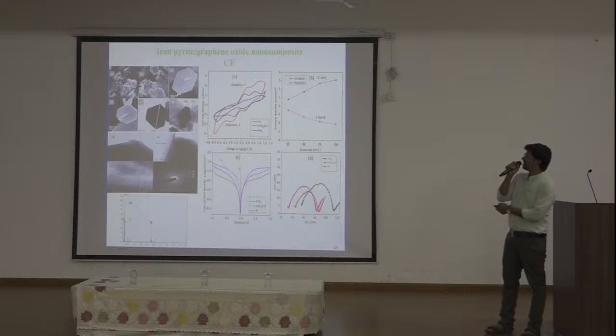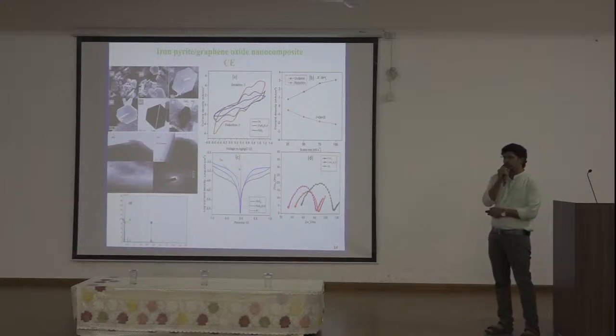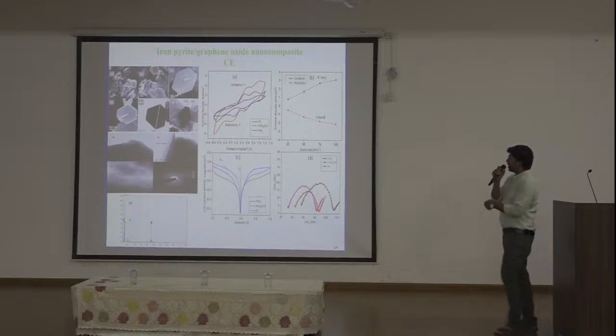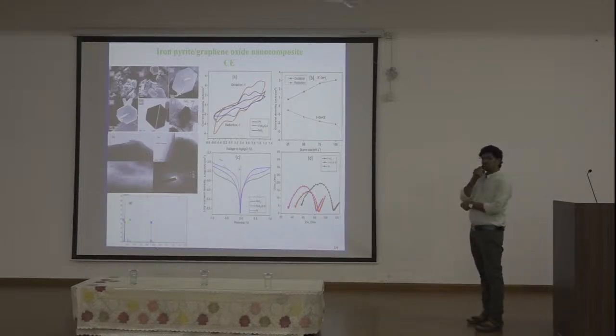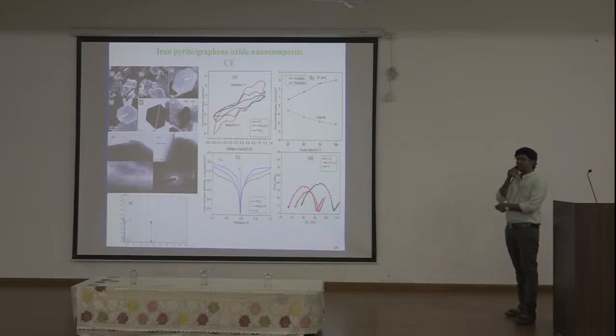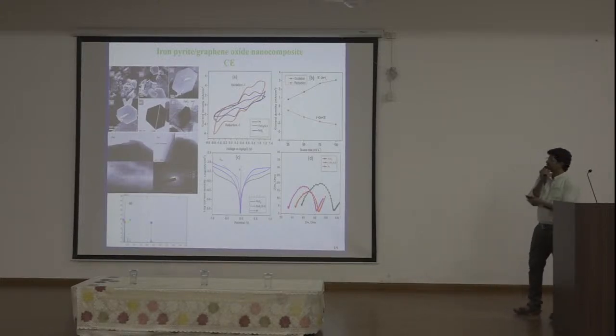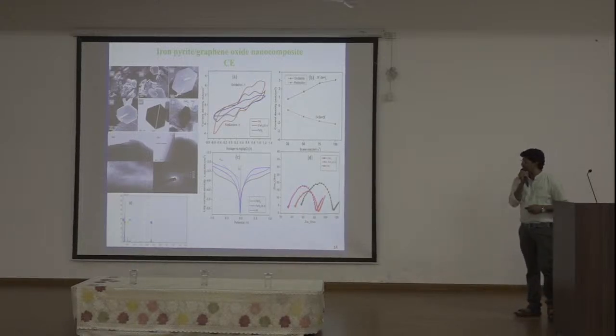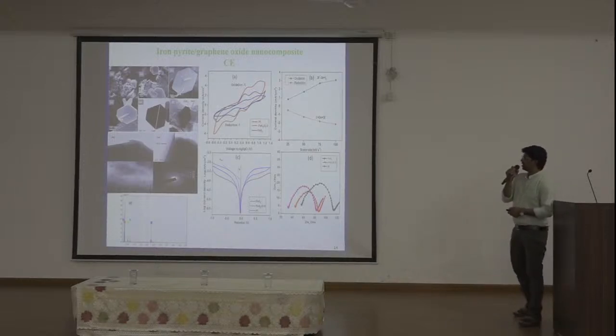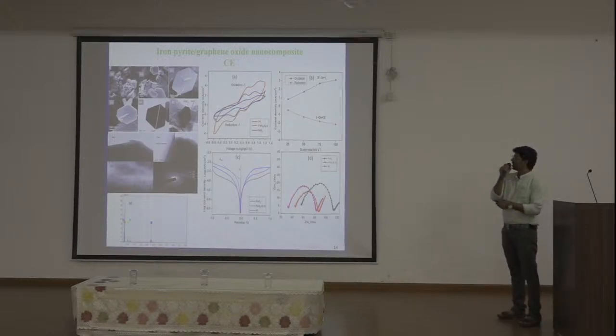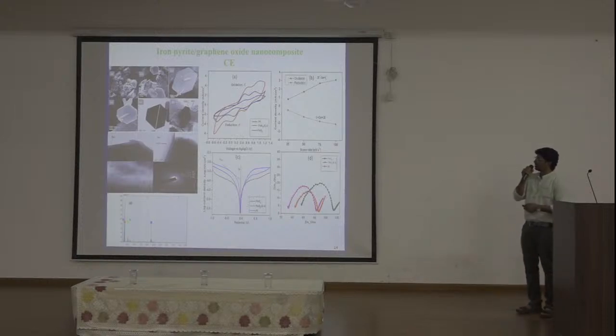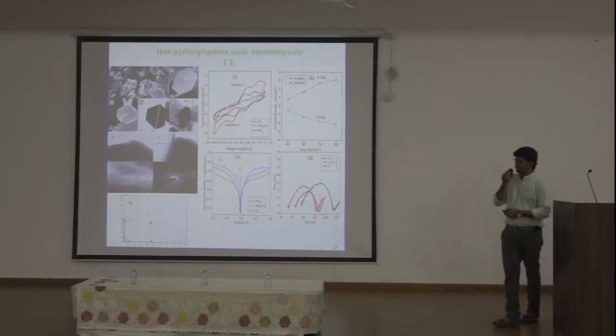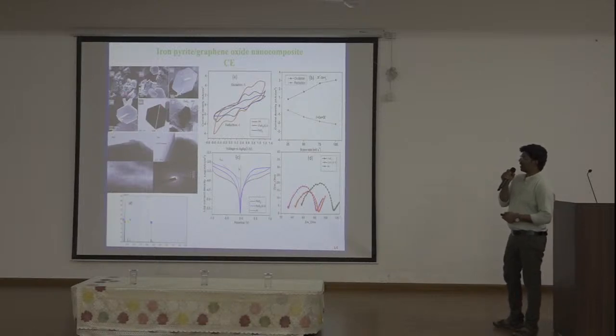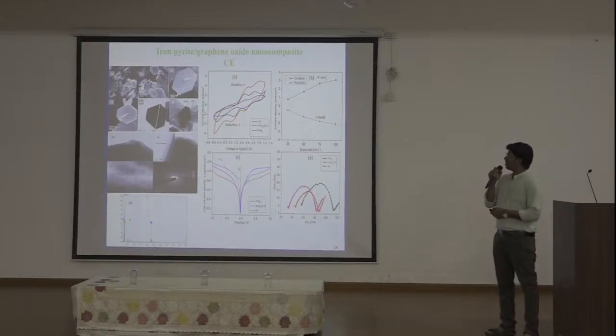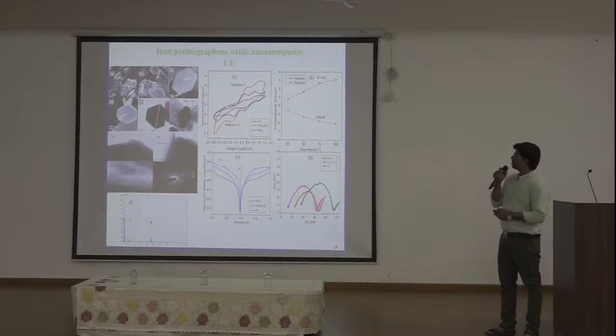Initially we tried iron pyrite and RGO composite. Second, we also tried the transition metal, especially the pyrite material, and its behavior as a counter electrode, checked in the graphene oxide composition. In this, I didn't show the basic characterization. Here with SEM analysis, we can see more agglomeration of particles in the FeS2, but after inclusion of RGO, the agglomeration of particles is highly reduced because of the graphene oxide.